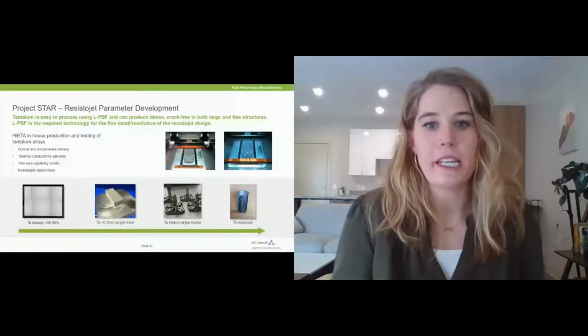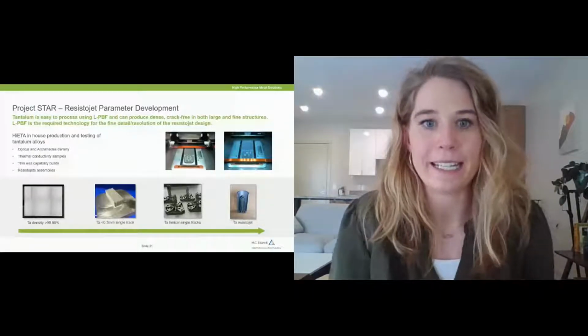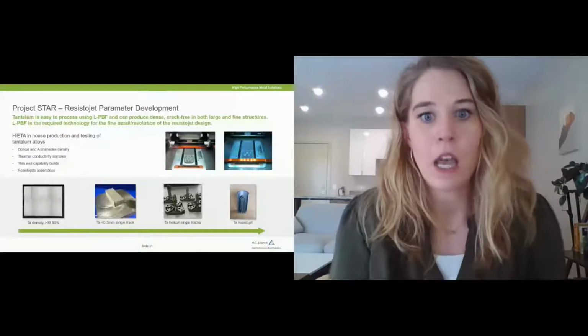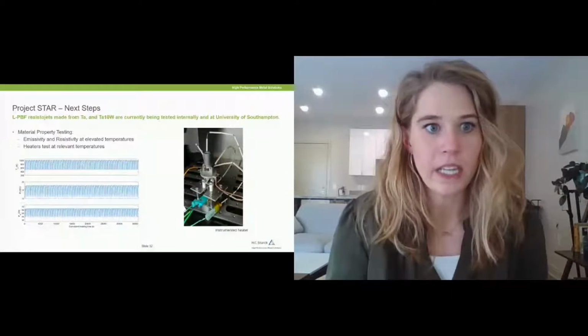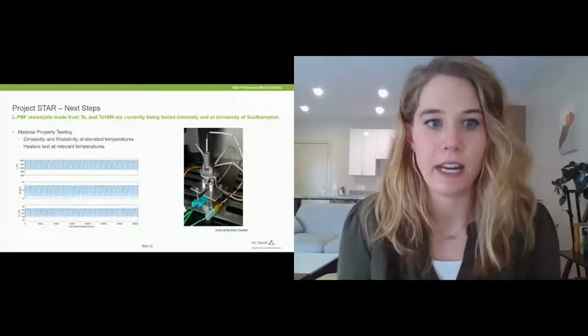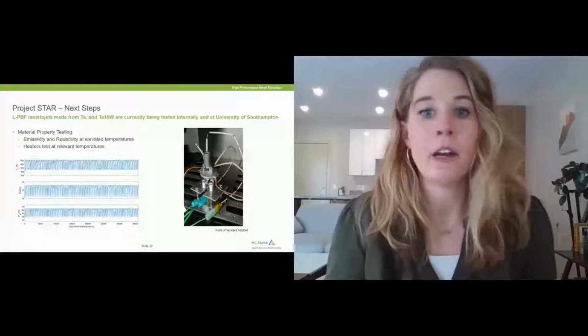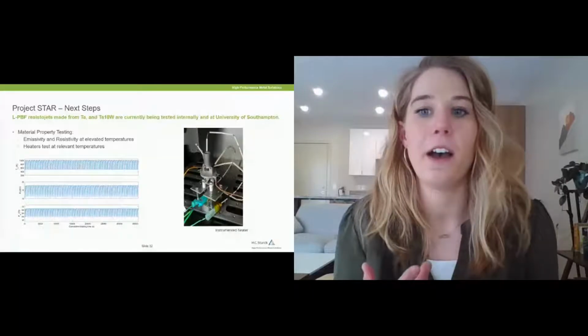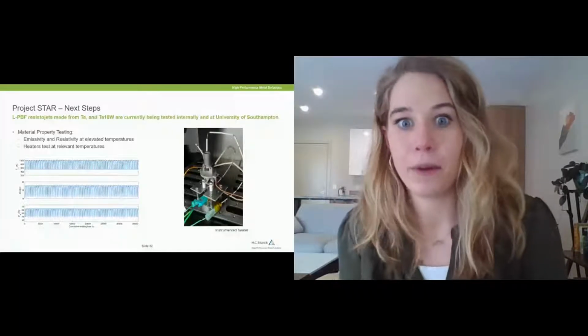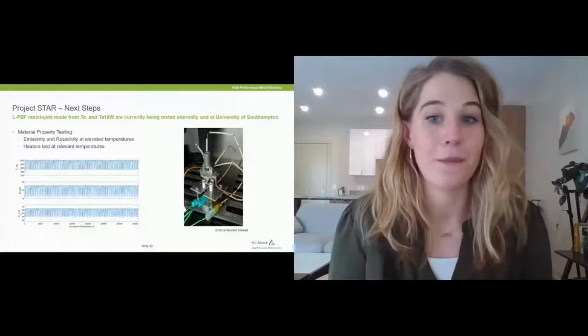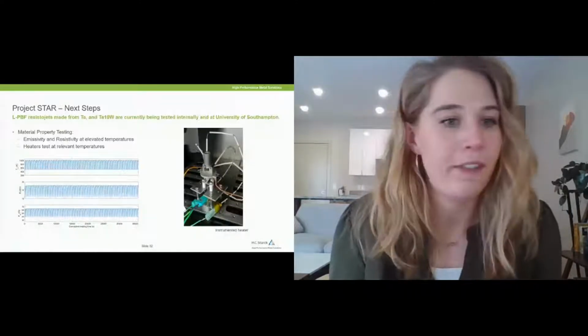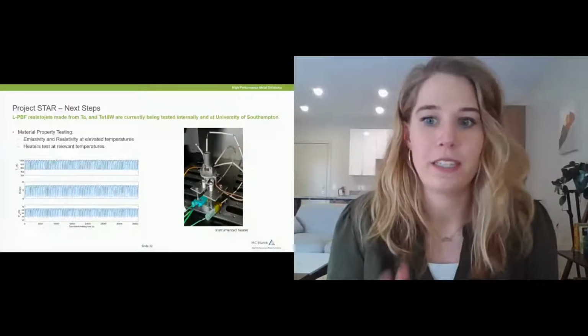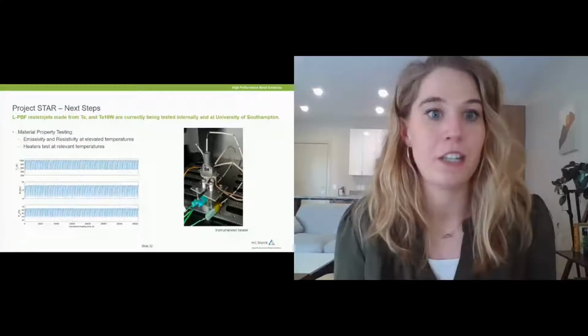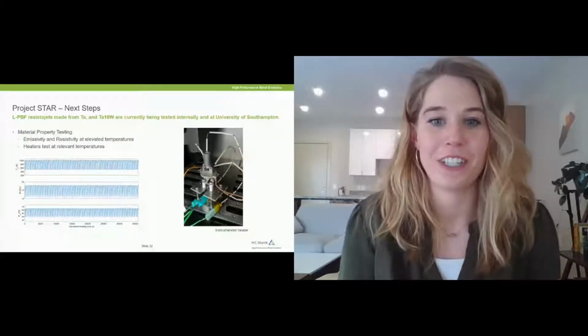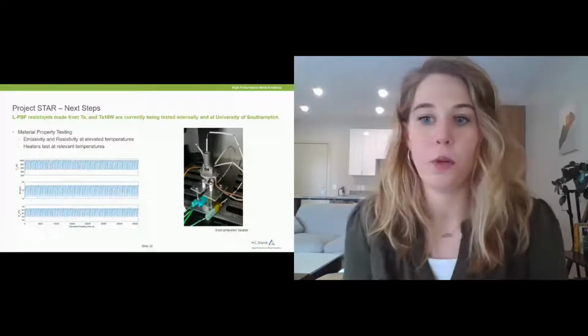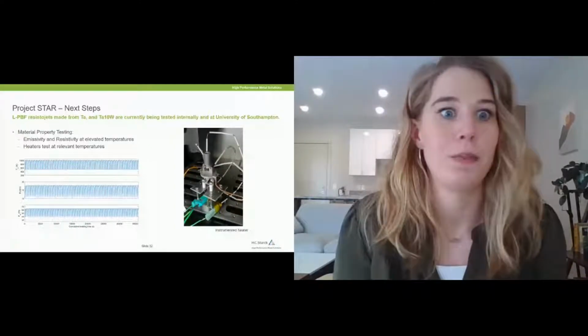So this is where we are currently. Currently, these resistojets are being tested internally and at the University of Southampton. The main things that they are testing here are material properties, such as emissivity and resistivity at those elevated temperatures. And also they're doing max heating tests and fatigue cycling tests at the operating temperature and max temperature. When I'm talking about max temperature, I'm thinking 2500 Kelvin. These cyclical temperature tests are meant to show the degradation of the resistojet over time. And so these components will go through over 4,000 cycles and over 100 plus heating hours.